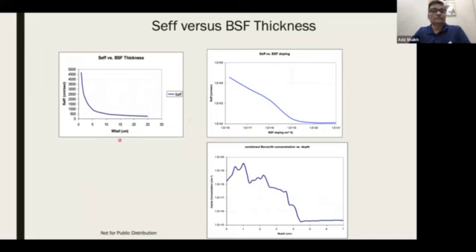So WBSF is the thickness of the back surface field, and S effective is the back surface recombination velocity. If you don't have any back surface field, then the recombination velocity is 5,000 centimeter per second. So a lot of carriers are being lost before they are being collected and used in a useful way in the solar cell.